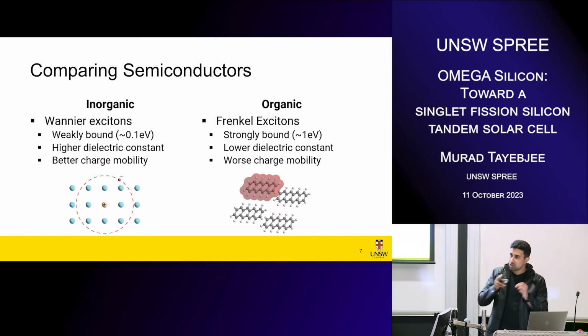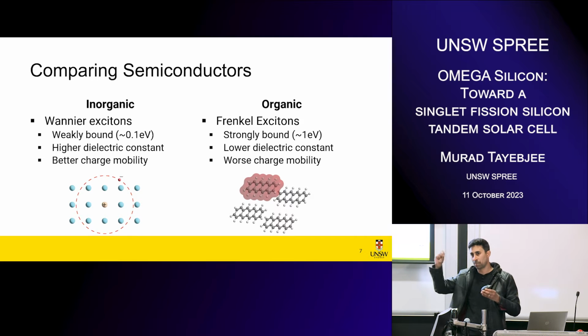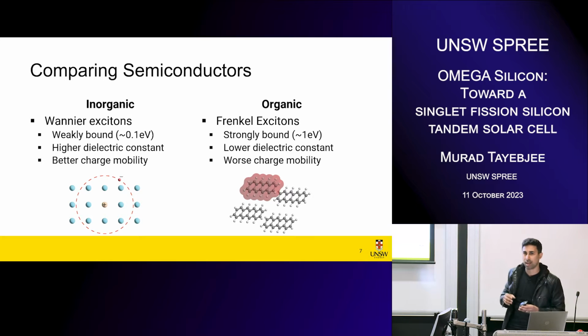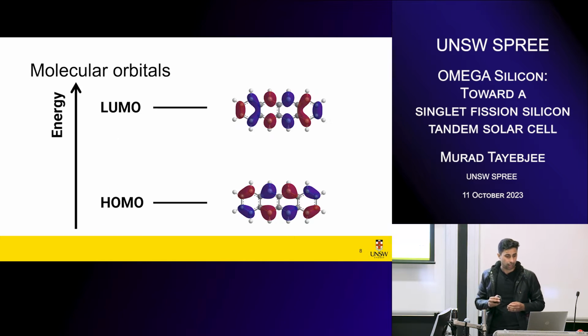Indeed, the way energy moves around an organic semiconductor is rarely just the charges hopping about, but it's more about the entire exciton jumping from one molecule to the other. So the Frenkel exciton sort of jumps about inside your device, and the charges will only separate under certain conditions, okay?